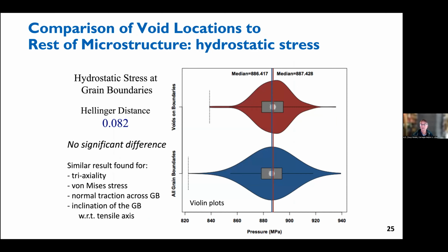So one of the first stops, as it were, was to say, well, surely it's the hydrostatic stress or the traction across each of those grain boundaries. So we looked for differences in the pressure across grain boundaries versus other locations. And so the red violin plot is for grain boundaries, and the blue is for the rest of the microstructure. And we could not find any significant difference. I mean, it really was a null result. There was nothing about the state of hydrostatic stress at the grain boundaries that could explain those voids.